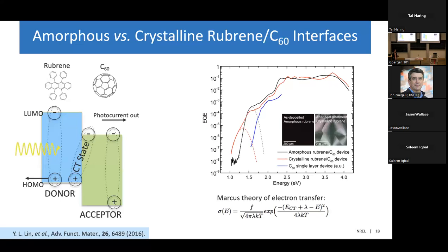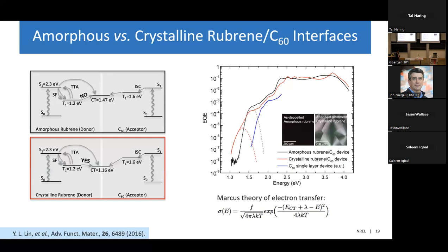And we can look at the photocurrent that's being produced by the device as we photoexcite it with different wavelengths of light. So here on the chart, I'm showing a semi-log scale of the photocurrent output from the crystalline and the amorphous rubrene C60 devices. And if we focus on the low energy region down here, we can see that they have quite different shapes. So this low energy region can be fit to Marcus theory of electron transfer to extract the charge transfer state energies associated with both of these interfaces. And from that, we can build the Jablonski diagrams for both amorphous rubrene and the crystalline rubrene C60 interfaces.